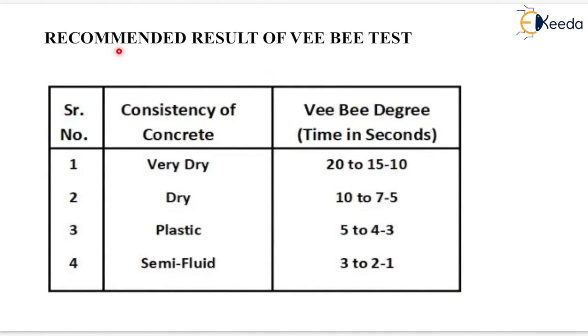Now the recommended result of the VB test is written in this table, that is the consistency of concrete, and here the VB degree, that is the time in seconds, is shown. For very dry consistency of concrete, the VB time varies from 15 to 20 seconds. For dry concrete, 7 to 10 seconds. For plastic concrete, 4 to 5 seconds. And for semi-fluid consistency of concrete, the time ranges from 2 to 3 seconds.